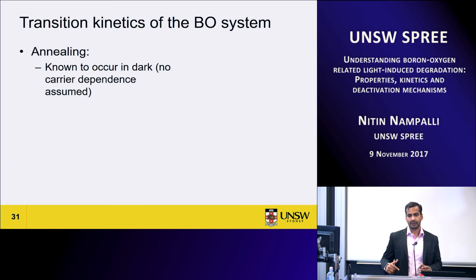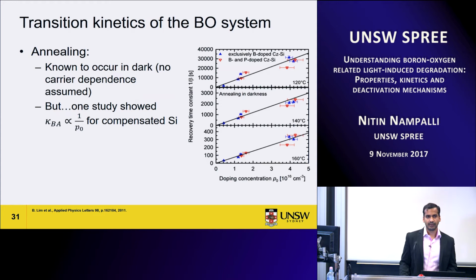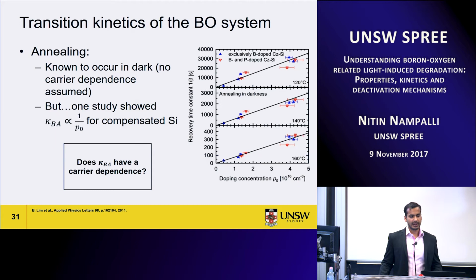This is typically done in the dark, and people have assumed that there is no carrier dependence because it happens in the dark. However, there was a study in compensated silicon that showed a dependence of the rate of annealing on the inverse of the hole concentration. So again, the question here is, does the annealing rate have a carrier dependence? But before we can really talk about